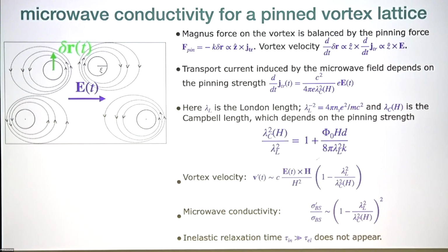Before discussing our results, I'll remind how this microwave conductivity is traditionally understood, within the Bardeen-Stephen picture. The picture is that the origin of dissipation is still friction, because the displacements of the vortex force causes friction. And what you really need to understand is the velocity of the vortices induced by the microwave radiation, and then substitute this velocity into the Bardeen-Stephen form. So even in the presence of pinning, the vortex velocity turns out to be proportional to the electric field, but it's not equal to the flux flow velocity. And so let me go through how to understand this.